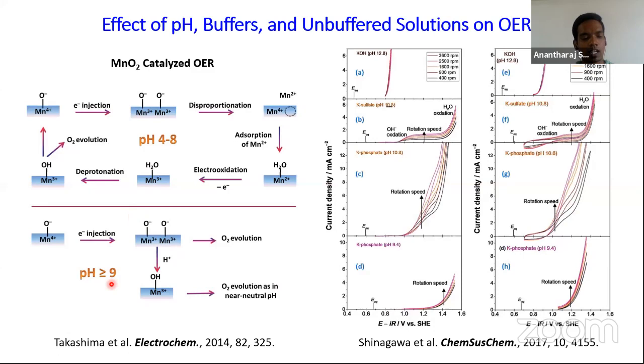But when pH is greater than or equal to 9, this process does not happen. This disproportionation does not happen. It directly goes on to evolve oxygen. So pH matters in neutral water splitting. It doesn't depend on the electrocatalytic material you use. It is the pH which is going to determine in which way the water electrolysis is going to occur.